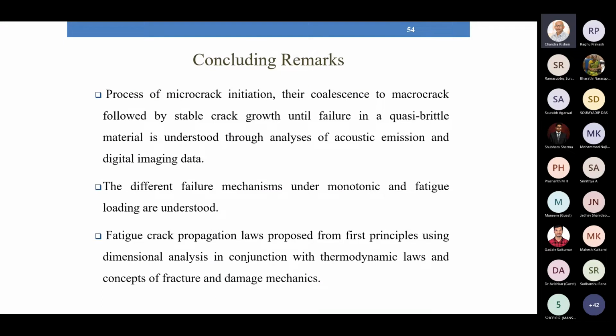So in conclusion, we have seen that by using acoustic emission and digital image data, the process of microcrack initiation, coalescence to macrocrack, and the stable crack growth could be very well understood in a quasi-brittle material, and the different failure mechanisms under monotonic and fatigue loading are understood. So what causes the failure under monotonic and under fatigue, and fatigue crack propagation laws are proposed from first principles using dimensional analysis in conjunction with thermodynamics laws and the concepts of fracture and damage mechanics.